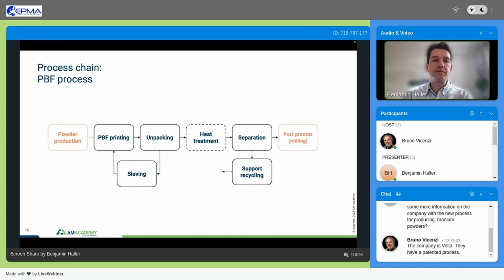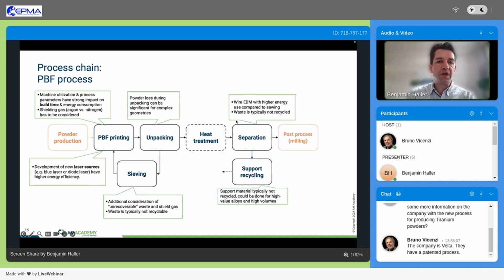Then briefly looking at some of the most important factors of the powder bed fusion process chain. Again, I want to highlight some factors. Importantly, during the printing, the machine utilization will have a very important influence. We will show later the impact of printing one part over printing a fully utilized build chamber. What is happening in the printing process right now is that typically the machines are using infrared lasers, which are not so efficient. And here we see new laser sources in development, like blue laser, green laser, also diode lasers, which will have a higher energy efficiency. So also on the printing process, there's a lot happening.